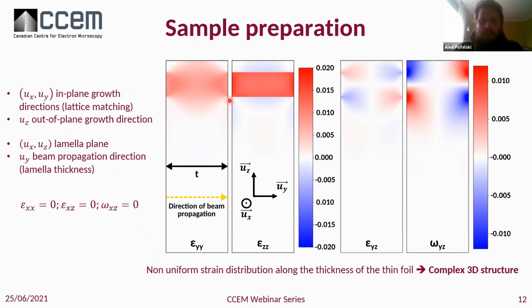What is interesting is to show what is happening along the Y direction, so along the lamellar thickness, and also in the growth direction. The first result that is very interesting is to see this. We see here a positive deformation. This is saying that there is no lattice matching between one of the in-plane directions and the substrate. This is the strain relaxation phenomenon that is appearing here.